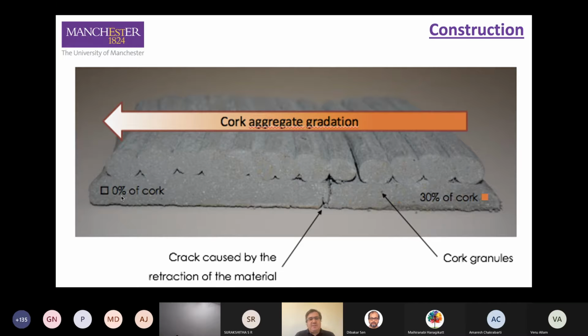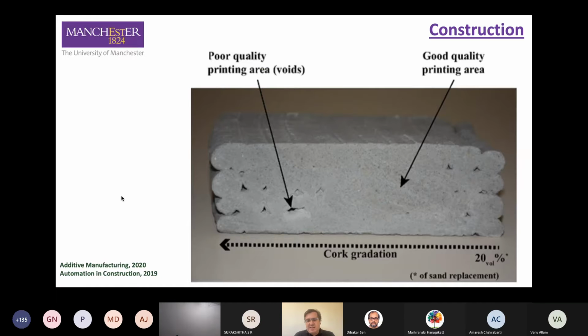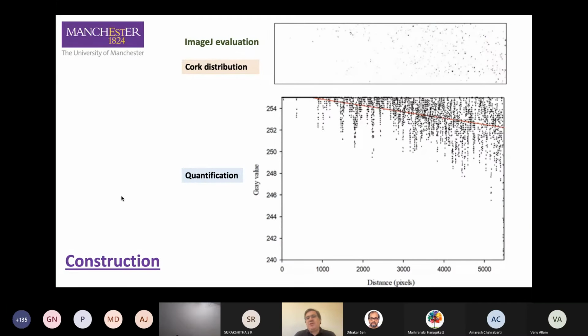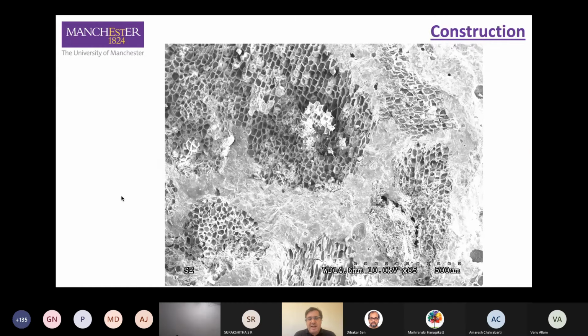So we spent some time optimizing the process, and this is another example of a structure, again with a gradient of cork. And by doing this, we can not only reduce the amount of concrete, and these images show that we have a very good control over the printing process and the mixture composition. But the use of concrete and cork allows also to improve the thermal performance of the construction element. So this is a scanning electron microscopy image showing some cork elements embedded in the concrete matrix.